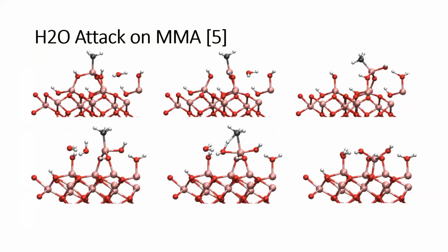There are a couple of differences between zinc oxide deposition and alumina deposition. Specifically, the alumina deposition has a TMA, trimethyl aluminum. It has 3 ligands rather than standard 2 with DEZ. There's another little caveat in here as well. Monomethyl aluminum, when we boil down to aluminum with 1 methyl ligand, it cannot be attacked by a single water molecule.